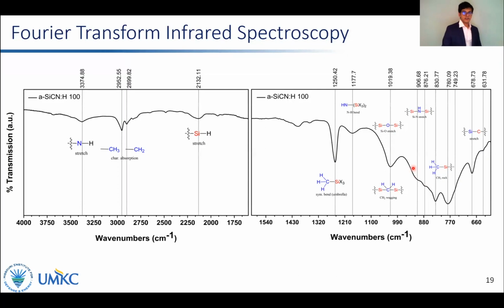FTIR infrared spectra were acquired on the as-deposited thin films, and the characteristic vibrational signatures have been assigned to chemical bonding configurations based on experimental and theoretical literature. Notable stretch assignments include NH stretch, several methyl and methylene stretches, which indicate the presence of terminal methyl groups and methylene bridges in the material.